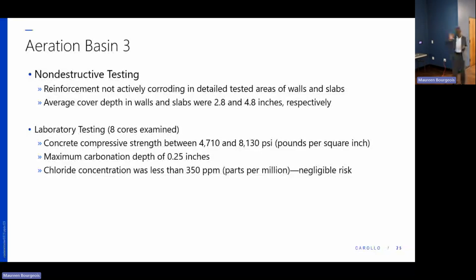However, for this structure, it's been in service for about 30 years. And so we are going to compare that to what the alkali silica reaction crack pattern looks like in comparison to the structure. For this structure at 30 years, ASR evidence is really minor, although we saw it in just 1 of the cores. Here's why we say that. The picture on my right, I should say, is a typical structure, not the SGRE structure, that has the crack pattern when you have ASR present. Some call it spider cracks because the cracks are all over the place usually, and you can't really stop it. However, the aeration basin is nowhere near that. And so we can say that it's minor, especially for this structure that's been submerged for 30 years. That's the scale that it ranks on.